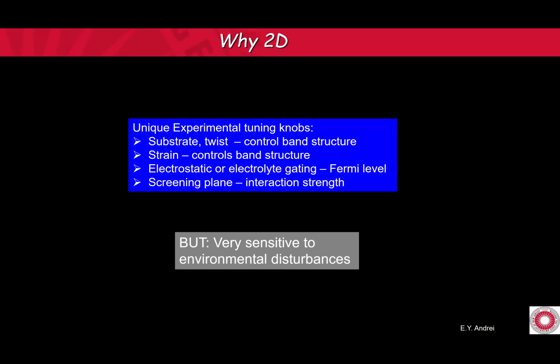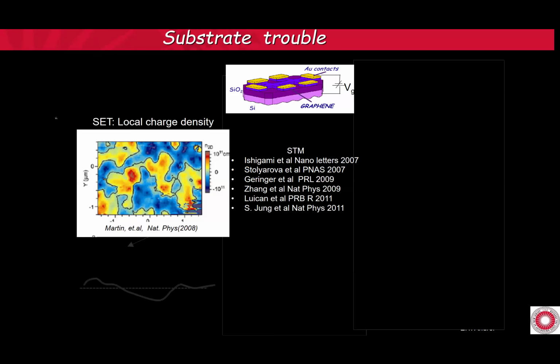You're just going to see your substrate. So that is a huge consideration and it's a huge problem for 2D material. Okay, to give you an example, in the old days, when people discovered graphene, the only way of making a sample was to deposit it on silicon dioxide, which is copied from the semiconductor industry. But then silicon dioxide is a horrible substrate. It has dangling bonds, it has charge centers, etc.